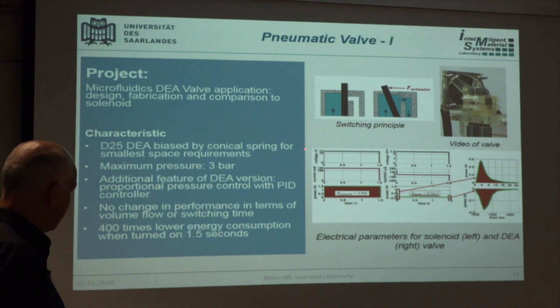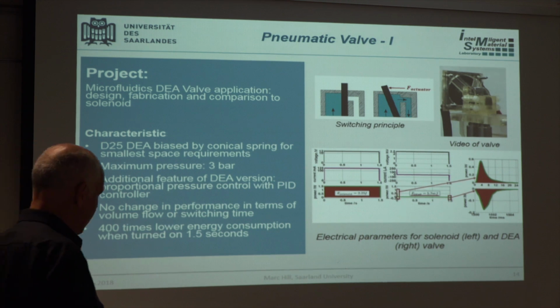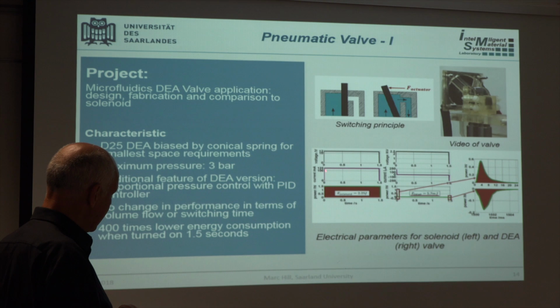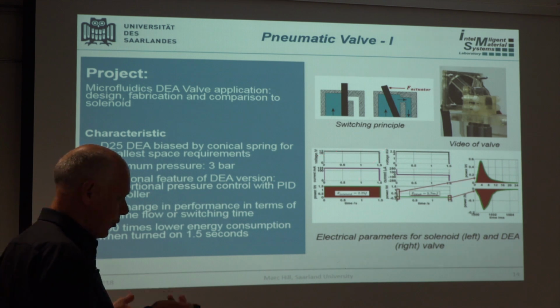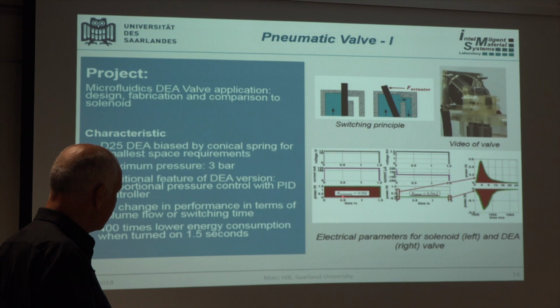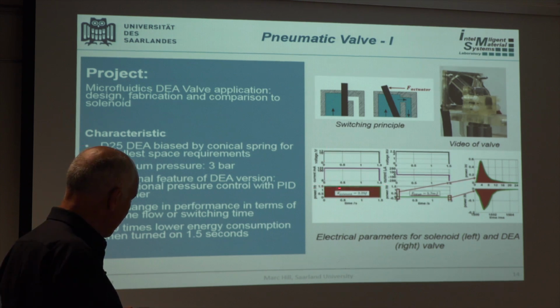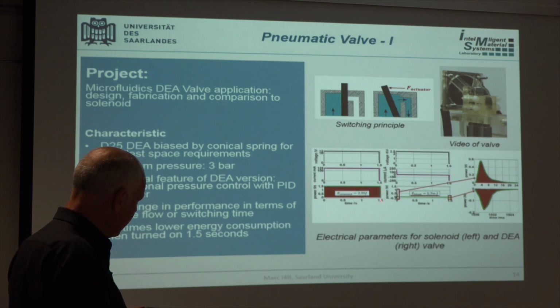And when we put it together, afterwards we could show that there is a huge potential for energy conservation. We looked at a process where for a second and a half you open the valve and then you close it again. When you do it with a solenoid, you have to apply constant current. And you easily see here, this is the power that you input, 1.5 watts over a period of 1.5 seconds, gives you an energy consumption of 2.25 joules.